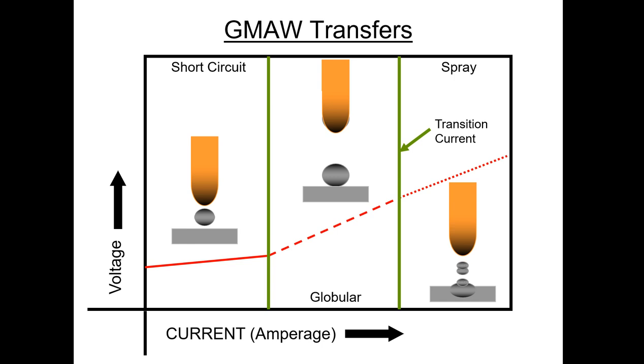Now the last one is known as spray transfer, where the globulars become very, very small and they're pinched off the wire and they're coming very rapidly. Now, we've hit a point where the wire feed speed is up and the voltage is up, and now the wire can't make it. The voltage is too high. The wire can't make it to the base metal before it gets pinched off. So now there's good plasma concentration. The wire's not out in front of us. We're not making spatter by bouncing the wire off the surface like we did in short circuit. So spray transfer is exactly where we need to be.